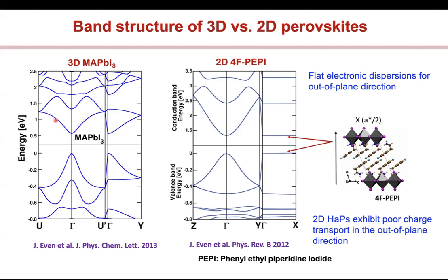material. And you can see these curves are very nice, which means that charge can really move across these valleys very nicely, right? Which means that when you put an electron here and move it, it has a nice slope on which it can move, and which means these materials have very nice dispersion, or curvature, where you can get nice mobilities in transport. Okay. So this is what the 3D perovskite is, and that's essentially the same for a 2D perovskite, except that this is for the 2D perovskites coming from the same octahedra, which is essentially the metal iodide bond that I have.